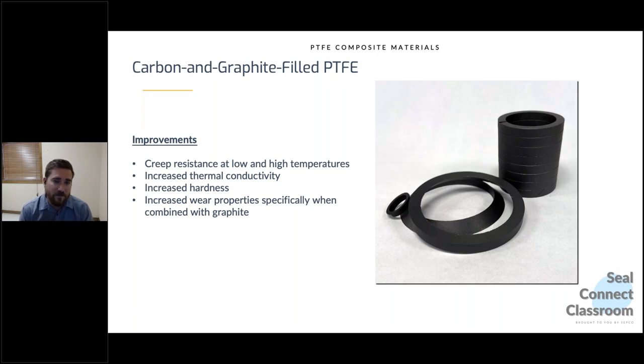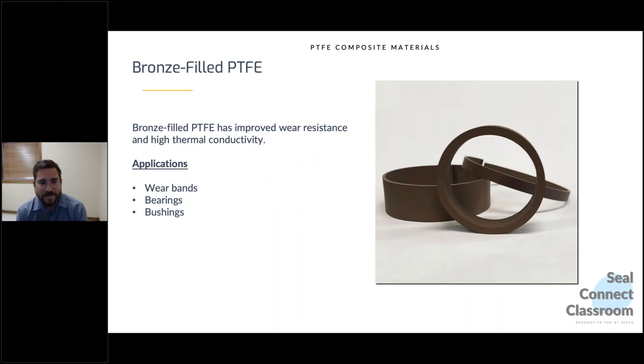So that is because of the improvements that carbon and graphite add, which is that it adds higher creep resistance, even at high temperatures as well as low temperatures, increases the thermal conductivity. So that's that heat dissipation that we want in a dynamic sealing application. We want the seal to get rid of the heat as quickly as it can, and at the same time be a hard, well-wearing material. Which is what carbon graphite does. So we'll go to the next slide.